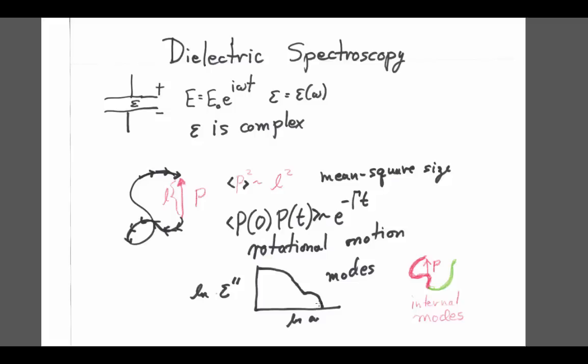Finally, if you are a really clever organic chemist, you could do the following. Note the red and green, the Christmas-colored chain in the lower right corner. The Christmas-colored chain has been assembled of two different chemical species, one of which has dipole moments, that's the red one, and one of which has no dipole moment. The one with no dipole moment does not contribute to the dielectric relaxation, and so when we watch relaxation, we basically are watching what one end of the chain is doing by itself.